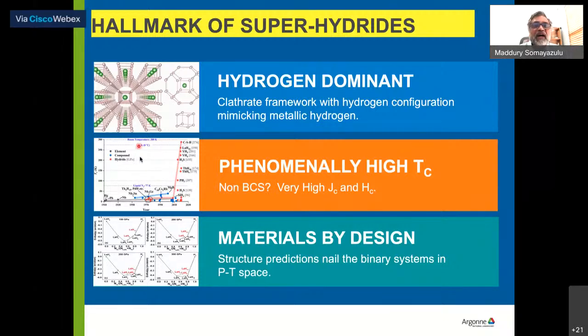Now, I have a plot here, where we have plotted where the transition temperatures have gone since the discovery of hydrogen. In fact, silane was one of the first hydrogen-dominant materials shown to have a high superconducting transition temperature. And you will see this huge jump in transition temperatures in a plot of transition temperatures versus pressure. So, phenomenally high TC.